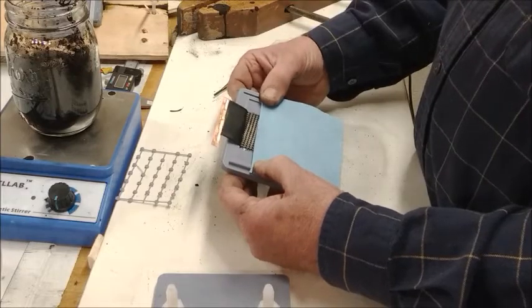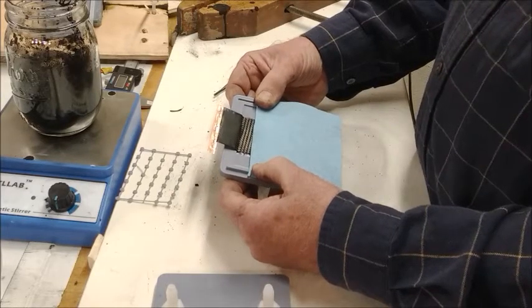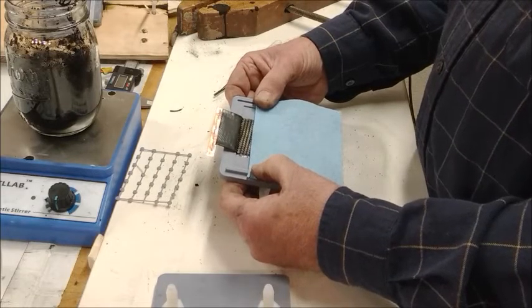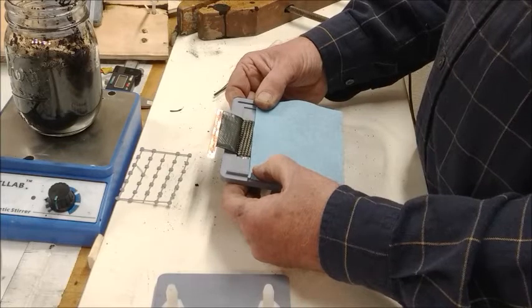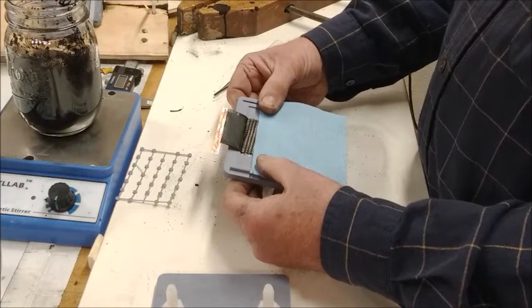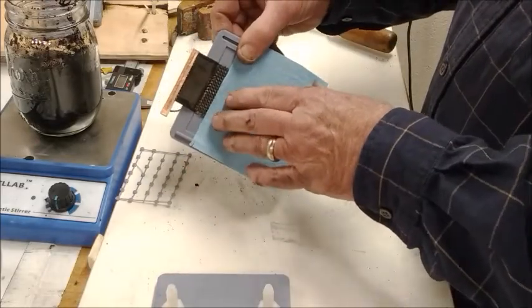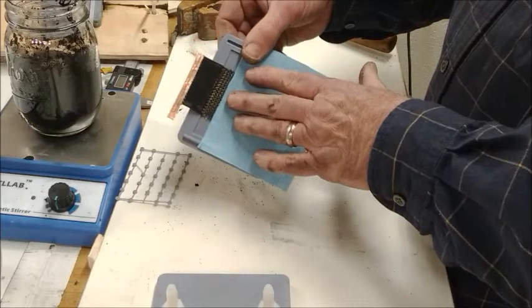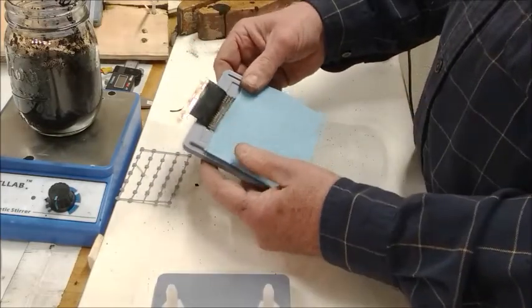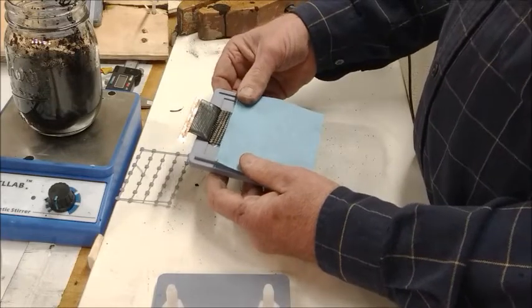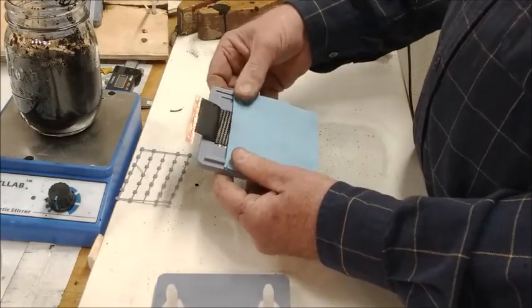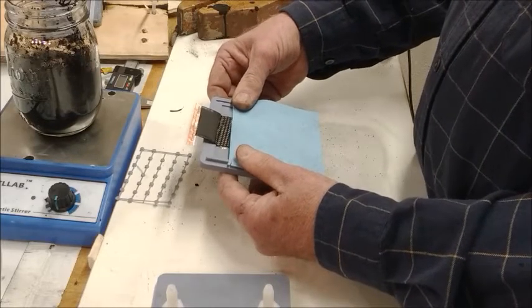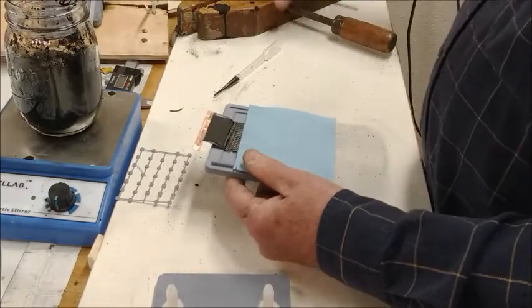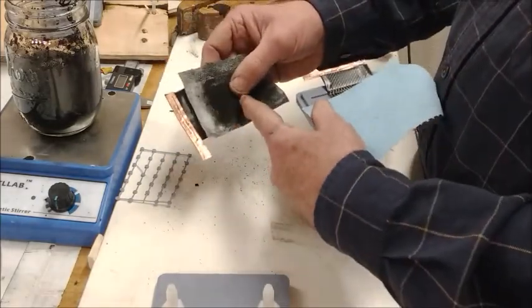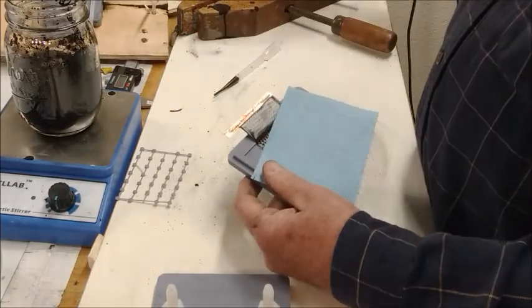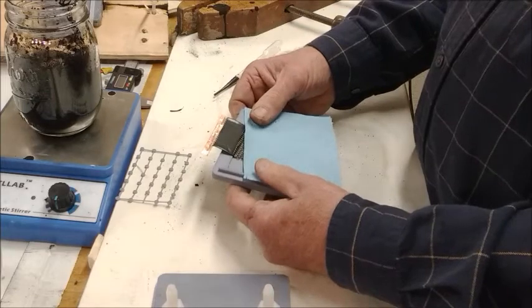And I figured, okay, the nice thin gap means that the ions don't have to travel very far, and that should promote efficient performance. And I guess it did, except that as I wet the cell, the wet towel soaks into the current collector. Basically the gap becomes close to zero and you get no flow. Well, let's just increase that gap, let's double it. Well, now the ions have to flow twice as far. There is twice as much material, but again, these are carbon particles that, unlike this earlier cell, are compressed and sandwiched together. Here they're floating, suspended in this KOH electrolyte.